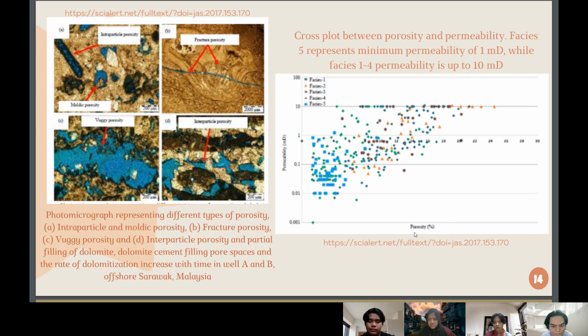The dissolution results in different types of porosity, which are moldic, vuggy, intraparticle, and interparticle. In fact, the dissolution process occurred in each phase, but it is more intense in facies 2 and 4, producing secondary porosity dominated by moldic, followed by vuggy, intraparticle, and interparticle porosity. Visible porosity varies from poor to fair in facies 1 and 5 and is locally good to very good in facies 2, 3, and 4. The porosity and permeability data of the various reservoir facies also show that facies 2, 3, and 4 have better reservoir qualities, while the tight limestone of facies 1 and 5 is characterized by poor reservoir qualities.